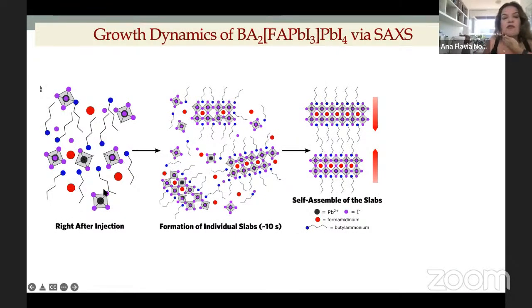So for instance, this was just after the injection. And then within 10 seconds, we start to see the formation of these individual slabs. As I mentioned before, this is n equal to 2. What does it mean? I have 2 layers of octahedra here, but I could also set the synthesis for n equal to 1 or n equal to 2, whatever, okay? So it depends on the stoichiometry. In this case, it was n equal to 2.